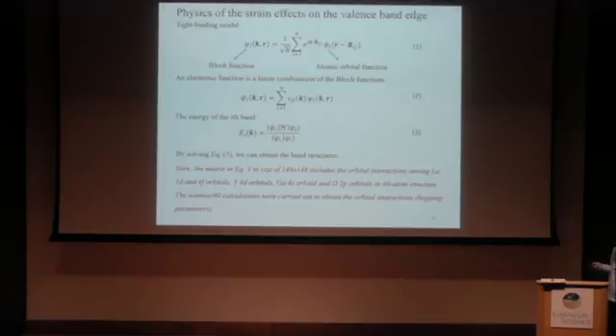And in the secular equation, the matrix is of size 148 by 148 and includes orbital interactions among the lanthanum d and f orbitals, yttrium d orbitals, gallium s orbitals, and oxygen p orbitals in this 40-atom structure. And the Wannier calculation will be carried out to obtain the orbital interactions in this matrix.